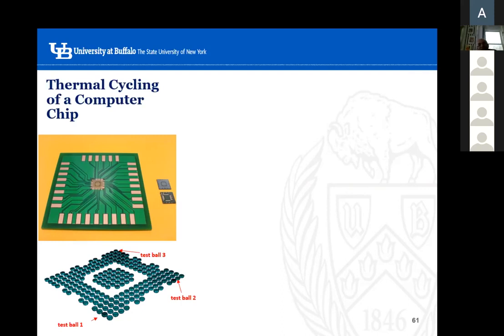Yeah, so when you use the Coffin-Manson equation, you have the plastic strain range, right? And then you must have the test data, and then you get the parameters A and B, which are the coefficient and the power over the strain. To get those parameters, you must have the test data, right? Without test data, there is no way you can get those coefficients. Here, I don't need test data, number one.